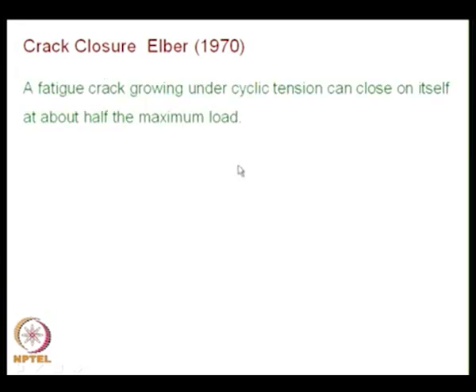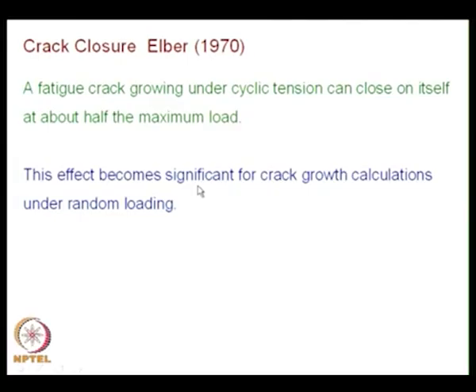So that is the reason why that chapter was covered earlier, and now we will take up a very important contribution by Elber. This was done in 1970. He brought out a concept called crack closure, and what he observed was that a fatigue crack growing under cyclic tension can close on itself at about half the maximum load, and this was purely an experimental observation. Based on the experimental observation, he arrived at this kind of a very interesting result. This effect becomes significant for crack growth calculations under random loading.